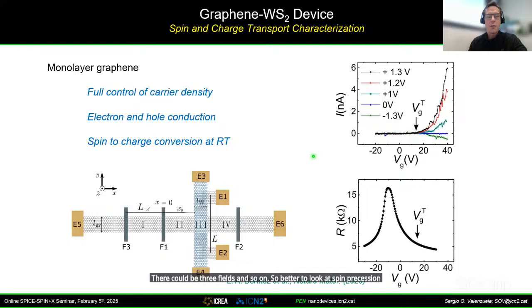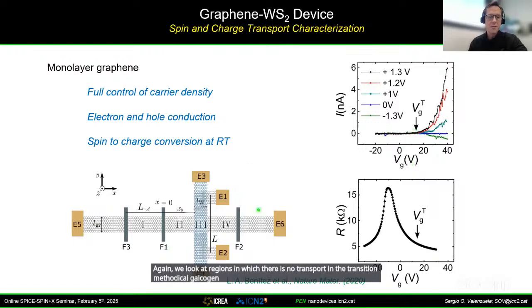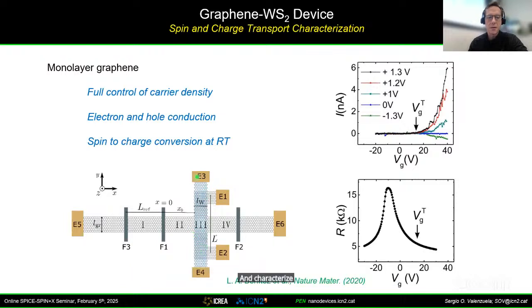Again, we look at regions in which there is no transport in the transition metal dichalcogenide. We have a device that is much more complex than what I showed you in the previous slide, with many electrodes to actually characterize the graphene, and characterize the transition metal dichalcogenide here and the region underneath graphene.